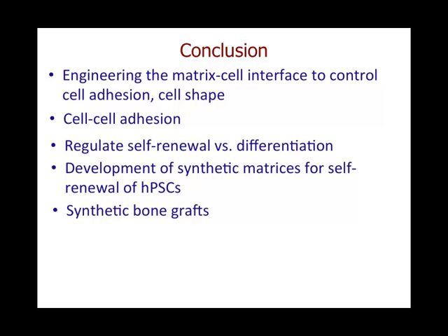We are very excited about the synthetic bone graft. Now we have a cheap alternative to allograft, or we don't need BMP. In the current market, 70% of the market is with Medtronic. They have an infuse system. There, you know, they have the BMP. So the BMP secretion or the movement of the BMP in the tissue can cause other problems like ectopic bone formation. So here we have a system which does not release any growth factor, nothing. It can direct differentiation and form vascular tissue.